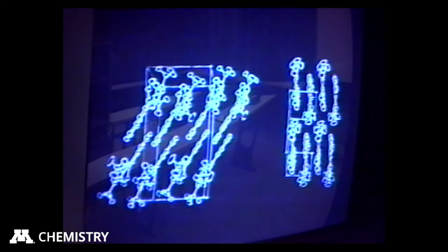We've done a lot of studies on the intermediate form of the expanded yellow crystal, and all we can learn is that it looks like a slightly disordered yellow crystal. We don't see any new phases. We don't see any amorphous material. So this is a real puzzle, but this is the kind of thing that happens with organic crystal chemistry. A lot of the phenomena have just not been studied yet, and being observant and being curious often has a very big payoff.